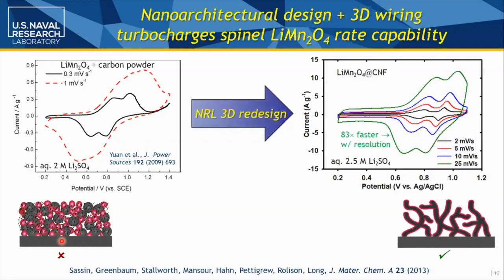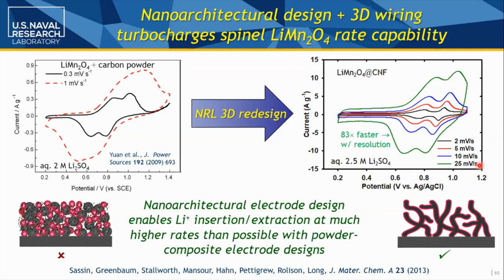But if you're doing what we do, where we've converted the birnessite to roughly 10 nanometer thick lithium spinel, you've got that resolution even up to 25 millivolts per second. So you can be 80 times faster in terms of accessing those electrons if you take the same material and architecturally design it. So that's typically what we want in the modern era. Yes, we want energy and lots of it so we don't have to charge our battery too often, but you also want power out of it in terms of modern devices. And classic powder composites are really hard to get power out of without compromising the chemo-mechanical characteristics of the active material. When you're only 10 nanometers thick, you really don't have to worry about it.